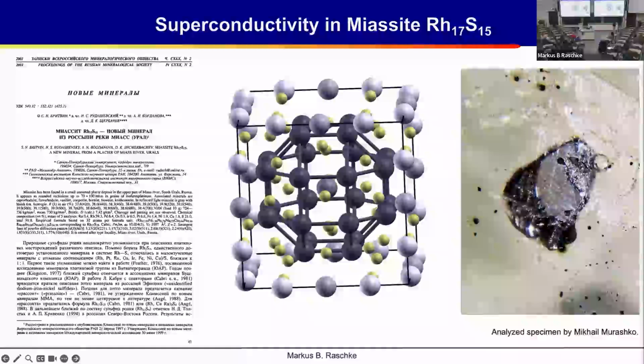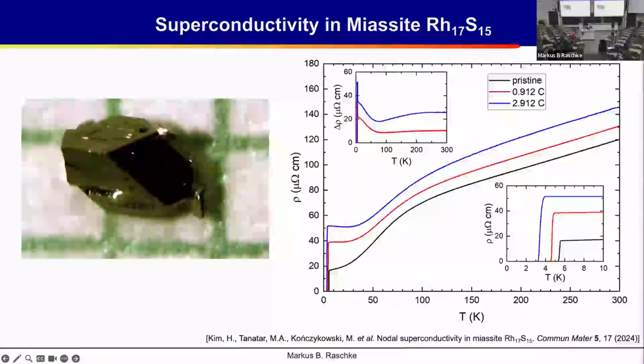And this is this rhodium sulfide compound. Now, these are very small crystals. This is actually just a small mineral inclusion, I think, in quartz. And it has a very unusual structure. So you have these sulfur atoms, and then you form these cages of rhodium atoms. And indeed, I think it was discovered in the Ural, and was indeed shown to be a natural superconductor.